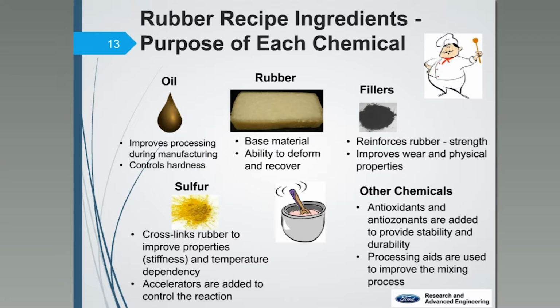When we talk about rubber, it's not just the rubber itself. There's many ingredients that go into making rubber. We'll start in the center there with rubber. It's the base material, and that allows the part to deform and then recover back to its original shape. Bob mentioned the oil, and certainly oil is really important in the processing of the rubber. It helps with the mixing of the rubber, and it controls the final hardness of the rubber compound. Another key component is the fillers, and that's reinforcing the rubber, giving it its strength and improving its wear and giving the rubber compound its physical properties.